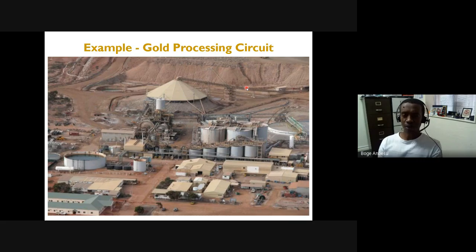Unless you understand sampling, maybe someone may just take a sample from here and say, this is my sample. If you do that, usually you end up with the wrong sample, and that's not representative anymore. But at least it needs to be done. Take time samples, could be every 2 hours, it could be maybe every 4 hours, whatever, but you need to take a reasonable sample by cutting from the